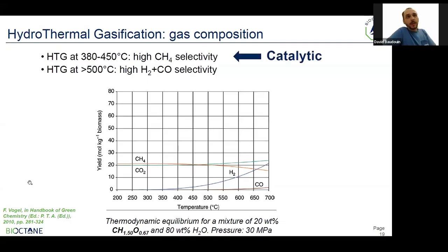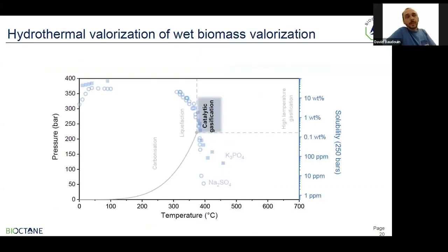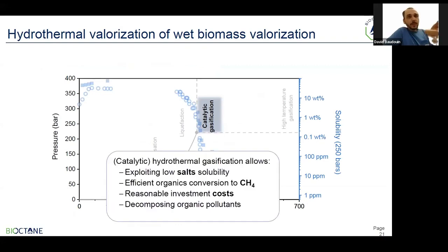And if you go to the next slides, I'm outlining that the lower temperature step involves the use of a catalyst, otherwise the reaction is not fast enough for a proper industrial process. Next slide, please. So the advantage of using lower temperature with regard to higher is that we can still exploit the low solubility of the salts because we are above the critical point of water. We have the advantage to be selective toward methane, which, depending on the objective, can be an advantage. It's easier to compress. Methane has this advantage over hydrogen. It's cheaper to compress. Also, it's a reasonable investment cost, as the temperature being much lower, the materials to sustain the temperature are much cheaper for investing in an industrial plant.